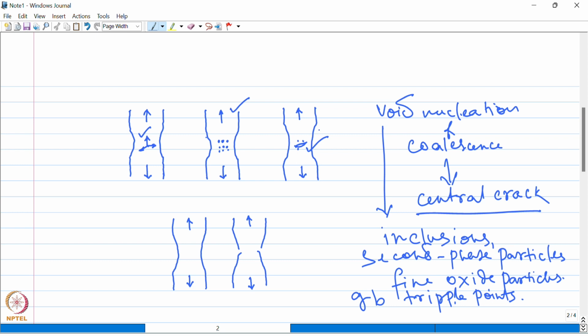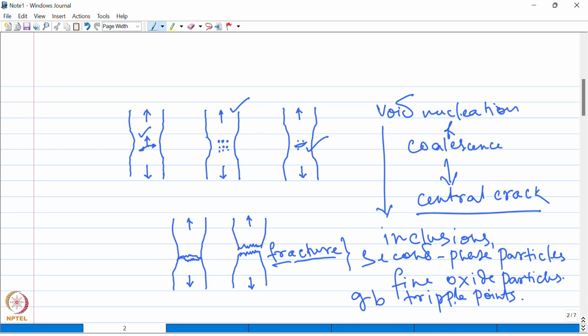So once this central crack forms due to the coalescence of the voids, this crack will grow as the material is being strained further, and eventually it will lead to fracture. So as the straining continues, this crack will grow and eventually this will lead to the fracture. These two parts will get separated from each other. So this crack propagates roughly at an angle of 45 degrees to the axis of the sample.